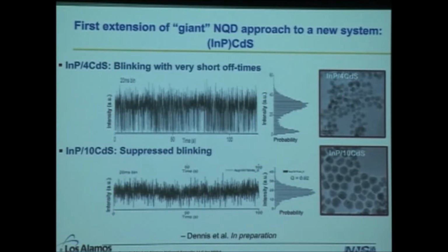In this case, we're looking at blinking effects. Even at 4 monolayers of cadmium sulfide, we have this sort of funky behavior where we're still blinking, but the off times are very, very short and almost characteristic. So this would suggest that this system might drive towards a single sort of off time or state. Whereas in cadmium selenide-based systems, this type of thing was not observed until the giant dot scenario. In the cadmium selenide-based systems, what you typically see is that there's no characteristic off time. So that itself is interesting, but then when we grow the shell thicker, we clearly see evidence of suppressed blinking.